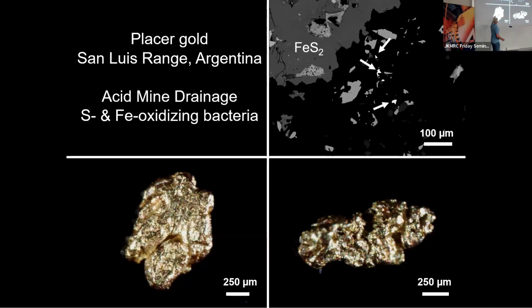And you can see within this that there's clearly discrete bits and pieces that have been cemented and glued together within this system. And so we were interested in looking at this process. And so one of the first experiments we did was looking at weathering of these materials, adding in our iron and sulfur bacteria, the same ones from our iron oxidizers, and see what we're going to get within this environment.